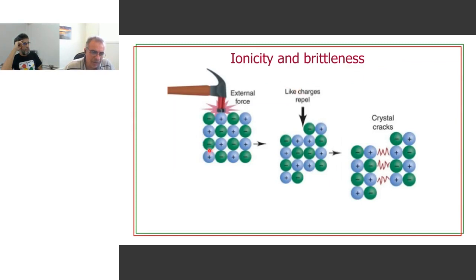This is a cartoon trying to explain why this is so. If you make some atomic rearrangement in an ionic crystal, it's important, for the stability of ionic crystals, that you keep global and local charge balance. This is very important to stability. If you locally break charge balance, you have very strong repelling forces that lead the system to crack.